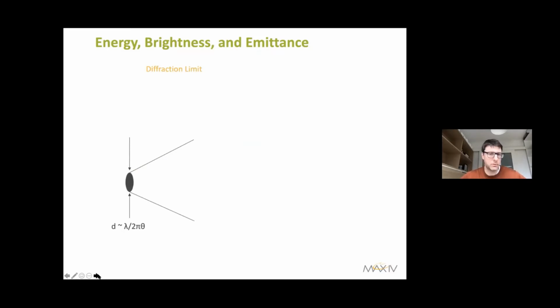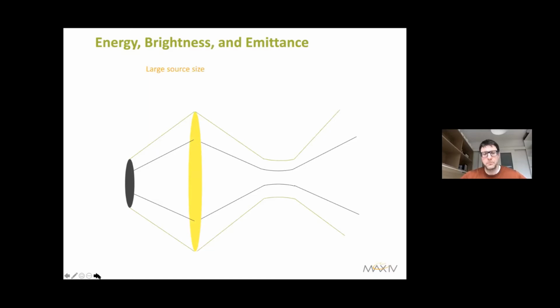Well, simply because of the so-called diffraction limit. If you take a source of electromagnetic waves or photons, and the source is smaller than the diffraction limit, which is proportional to lambda over the numerical aperture, then by using some kind of lens system we can focus it down to the diffraction limit dimension, and that's the probe size with which we can, for example, raster scan our sample and make maps of whatever properties we are looking for. If the source size is larger than the diffraction limit, then it starts influencing the size of the focus and compromises the resolution, the spatial resolution in particular.